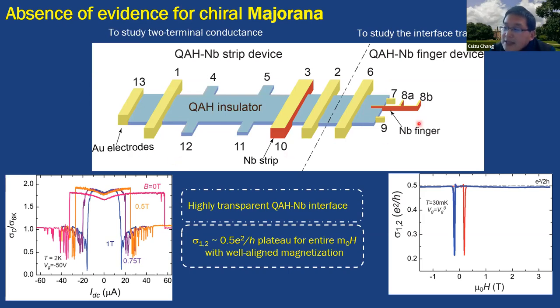You know, on this kind of sample, we performed a two-terminal measurement on this side. We can see that it shows this kind of e squared over 2h, but this is different from the theoretical prediction. According to the theoretical prediction, the observation of this e squared over 2h can be considered as the formation of the chiral Majorana in the quantum anomalous Hall and superconductor layers. So in order